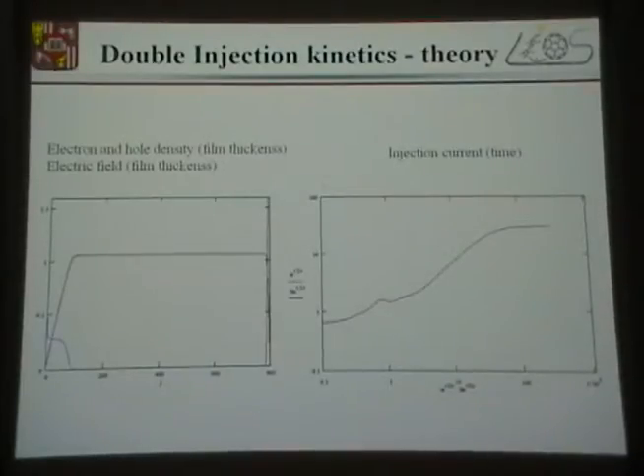And here I have a very nice simulation movie where we calculate the electron and hole density during the double injection in the film. It's time dependent current, so on this axis here we have the electron concentration, that's in blue. Here we have the hole concentration, that's in red. This is simply the electric field distribution, so if we apply some 1 volt to the film in forward bias, we see what happens in time. And here on this axis we have the injection current as a function of time.